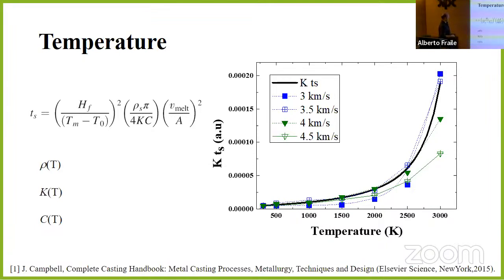Solidification time depends on different parameters like the density, thermal conductivity, heat capacity, and the temperature. So this is something that, well, we are working on it, but couldn't find good models for this. So this is something that is quite unexplored, and is very important because the simulations we did at 300K, but the material in the tokamak, for example, won't be at 300K.